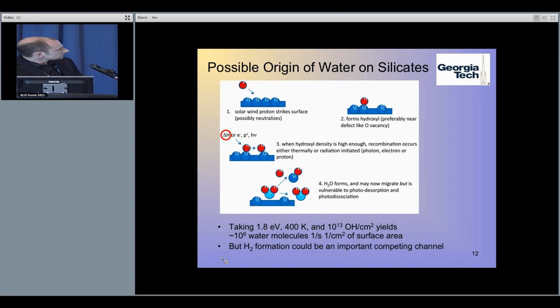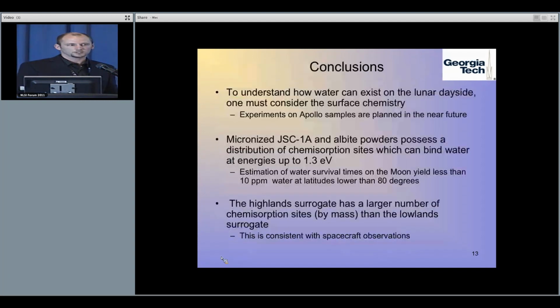And I've shown just some values that I tried out. This is from the initial heating recombinative desorption we observed. This is the middle of the peak, 400 Kelvin, and this corresponds to about 1% of a monolayer of hydroxyls on the surface. A very simple calculation yields 10 to the 6 water molecules per second per centimeter squared of surface, which is about 1% of what I understand the flux of the solar wind is. But it's unclear whether this will all come off as water or whether we could get hydrogen instead. So that's a competing channel that we are looking into.